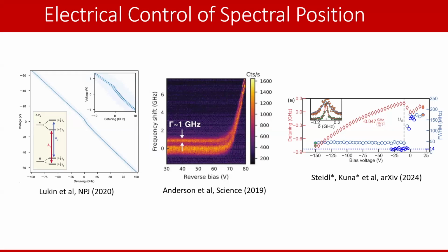And also, in optoelectronics books it says that for the electron to go from the metal dielectric junction, do you think the doping matters in silicon carbide? It absolutely does. And this is why we have Schottky contacts and not ohmic contacts. The material that we're using is as lightly n-doped as possible, because there is the HPSI material that you can buy from Cree and so on. These guys do dopant compensation, so they'll put p dopants in to give you an intrinsic silicon carbide, but these dopants are bad for defects, right? Anything that's not your perfect crystal lattice is bad. And so we use this extremely lightly n-doped material. And by lightly n-doped, I mean 10 to the 14 n-dopants per cubic centimeter. As a result, all the contacts will be Schottky contacts.